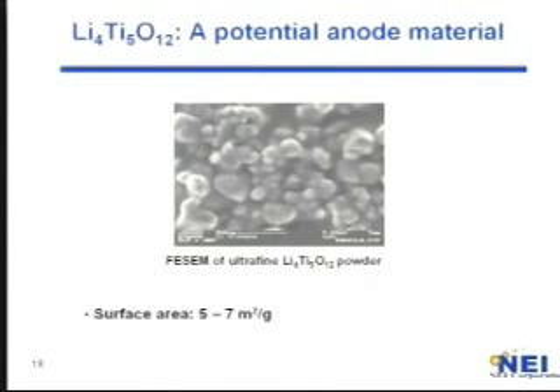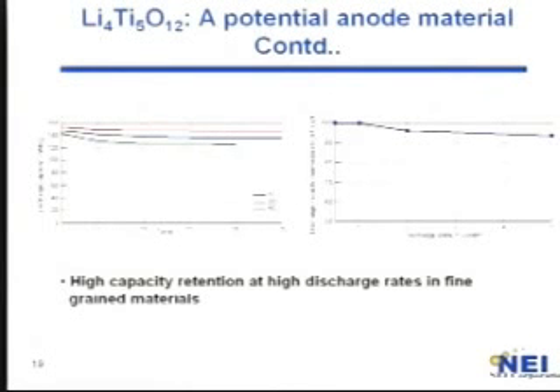Again, here is a FESEM micrograph of this material. The surface area of this material is around 5 to 7, which is not significantly high in terms of considering a nanomaterial, but this material is composed of 100 nanometer crystallites. This is something in between nano domains and nanoparticles, where the surface area has moved up, but it also has nano domains. And again, here just to show the discharge rate capability of this material. Again, 1C is, as I said, a 1 hour discharge, 5C is a 12-minute discharge.